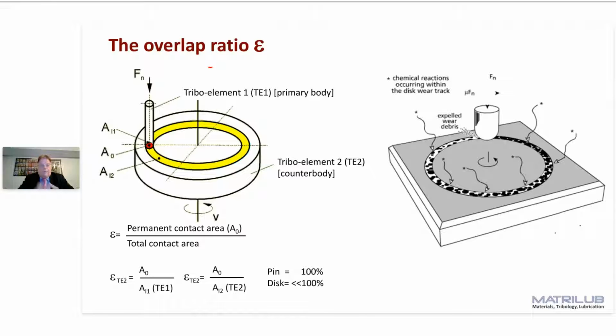And a very important point in tribotesting is also the so-called overlap ratio. The overlap ratio, epsilon, is a ratio between the permanent contact area, in this case the red area of a flat pin, divided by the total contact area, which is the wear track on the disk. And also here you see one tribo element is in contact all the time, and a surface element on the rotating disk has some vacations during the test.